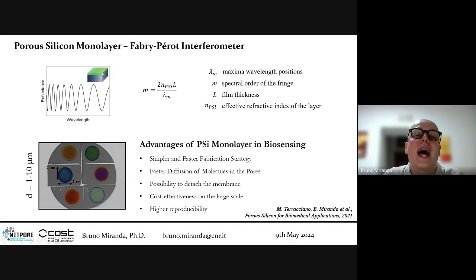So I can characterize the thickness of this film by using, for example, AFM or scanning electron microscopy, by tilting the sample and measuring the height of the pores, and knowing with the Bruggeman model the porous silicon refractive index. So we can predict this shape and tune where the maxima positions of this spectra will be.